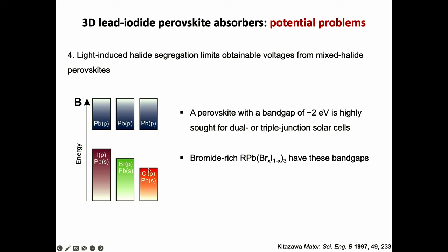So this is really nice, because if you mix bromide and chloride, you can get these intermediate band gaps. And likewise, if you mix bromide and iodide, you can get the perfect band gap you want for a tandem solar cell with silicon. Except that if you make this tandem solar cell, it does not behave like a mixed halide perovskite. It behaves like an all-iodide perovskite. So the voltage, no one has been able to get the high voltage they expect to get by mixing iodide and bromide together.